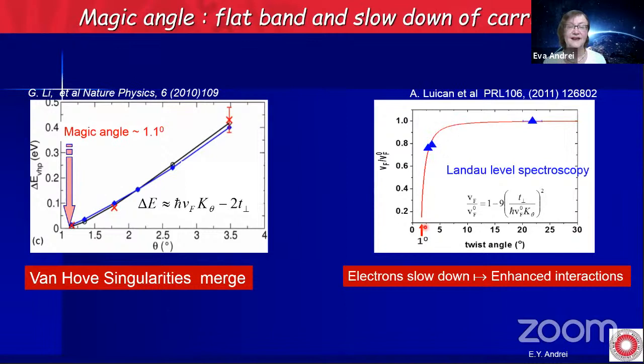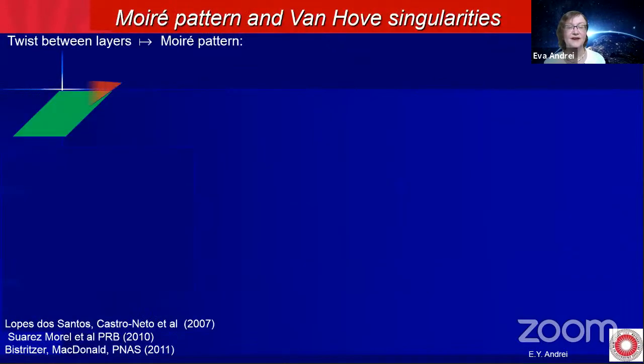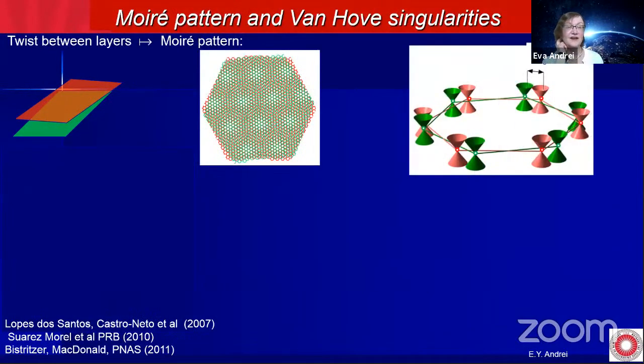And you see that at about 1 degree, the Fermi velocity vanishes, which means the electrons slow down so much that they can now interact with each other. And this is where you expect to have a correlated state if you bring the Fermi energy within that flat band. So this is 1.1 degrees, that's where it looks like you create a flat band. So what's going on and why do we create a flat band?